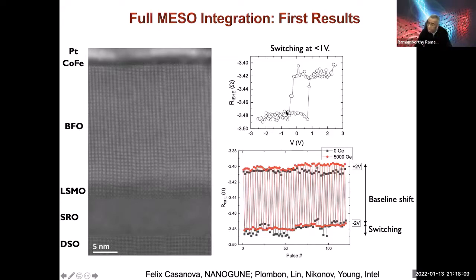The magnitude is small because for these structures, cobalt iron with platinum, that spin Hall efficiency is very small, maybe 0.1 to 0.2. But indeed, we can switch it back and forth with electric fields, showing you that you can do this work of creating the MESO. Another question is, how does one manipulate this to make it even better?